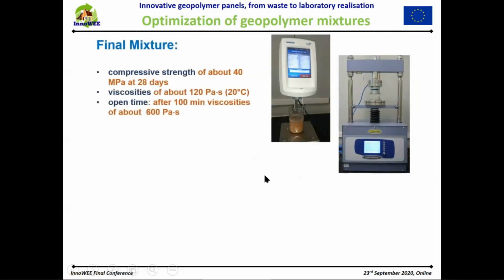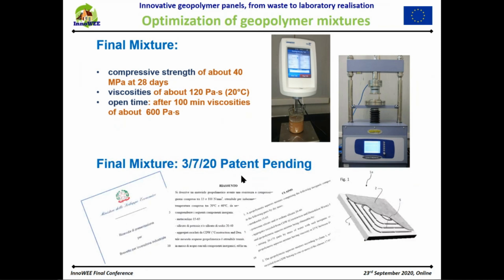The final recipe that has been obtained with the best of the parameters we have described is a compound that has a compression strength of about 40 megapascal at 28 days, and viscosity about 120 pascal seconds, and open time after 100 minutes with a viscosity of about 600 pascal seconds. Starting from this recipe, a patent application was filed. The aim was to protect this invention, and together with the recipe, we have also protected one of the most performing products obtained, the radiant ceiling panel, which has shown particular efficiency properties, and we talk about this in the next slide.